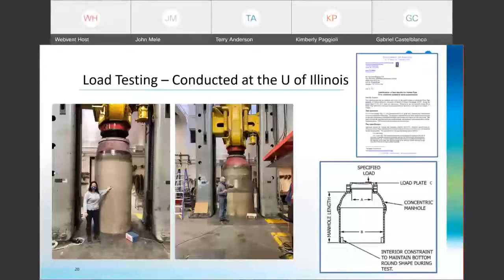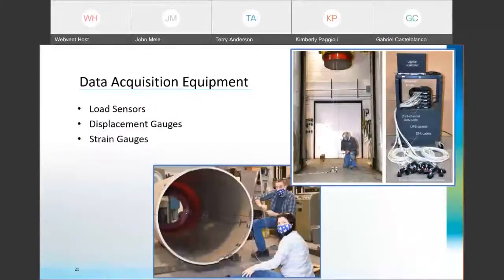The test was performed as outlined in the standard, with the complete cover and grade ring installed and the specified load applied concentrically on a 6-inch by 6-inch by half-inch steel plate resting on the manhole cover. Before the testing was performed, a series of sensors and gauges were installed. During the test, we were able to record the vertical displacement of the 6-inch plate relative to the floor, the total load on the manhole, as well as taking strain measurements at various load levels.